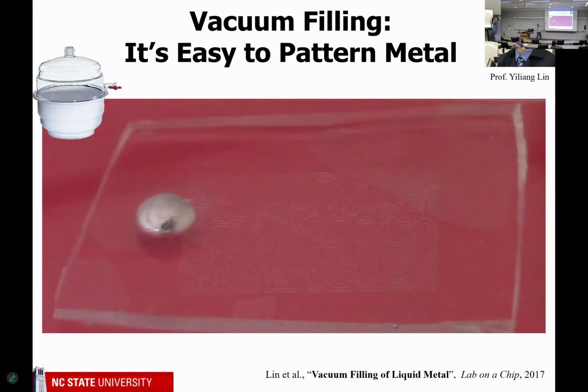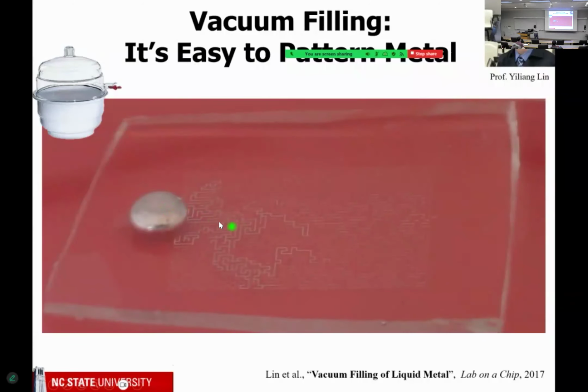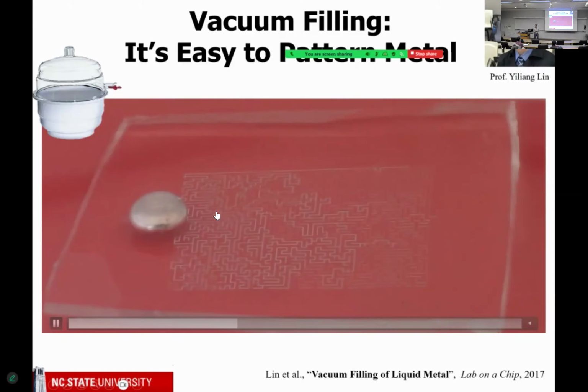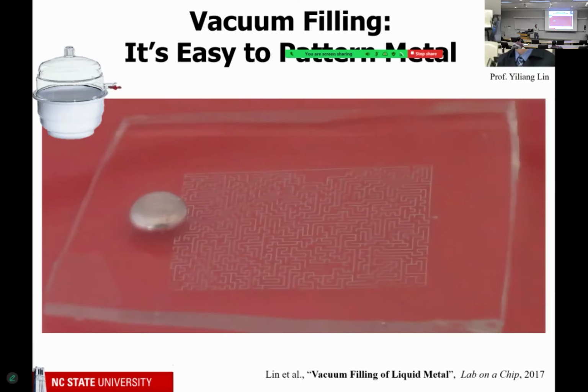We put that into a vacuum, and we pull all the air out, which actually renders these channels under vacuum. And then one of the cool things with liquid metal, you can see the reflection of the student. This is when he was a grad student, now he's a professor. But anyway, you can see his reflection as he turns the valve to the chamber, which lets the air back in. And this will cause atmospheric pressure to push right here. And these are still under vacuum, and so it pushes the metal in. Very, very simple, hands-free fabrication.